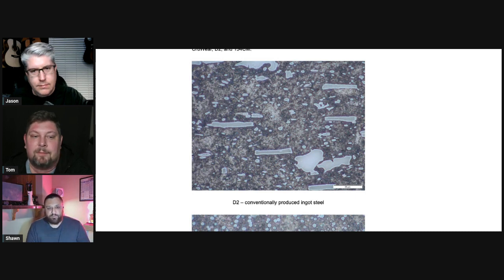We know they're chromium carbides because of the chemistry of D2, and typically you can look up a lot of literature that will say that that's what these are. These are chromium carbides. And we can see right here that these are incredibly large. That's 20 microns right there, the scale bar. And a red blood cell, for reference, is about 8 microns. You can't see a red blood cell.